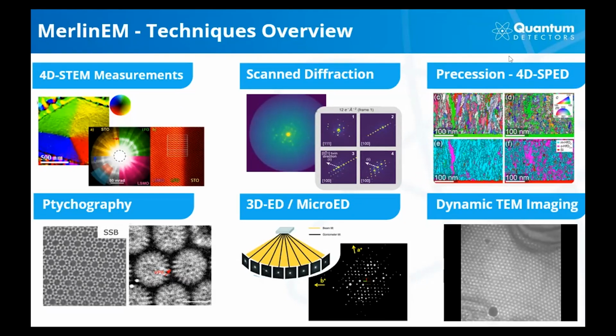So scan diffraction with or without precession, or tilt series reconstruction. Tilt series reconstructions are becoming quite more utilized. Also, an additional topic is dynamic TEM imaging. Because of the fast frame rate, we can actually look at some specific experiments. So in this case, this is a skyrmion crystal where a couple of skyrmions are getting created and annihilated, and the detector can capture this sort of detail because of the fast frame rate.